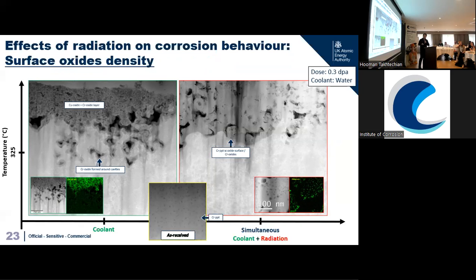When we analyze the chemical distribution, we know that chromium does form a protective layer against corrosion, which is why we put chromium in the copper. For the material exposed to just coolant, we see good chromium oxide formed at the surface, about half of the copper monoxide and dioxide. But if you compare to the oxide that grows under coolant and radiation environments, the chromium is no longer forming protectively. It is precipitated out. So that changes the mechanism of how corrosion actually works under radiation environments.